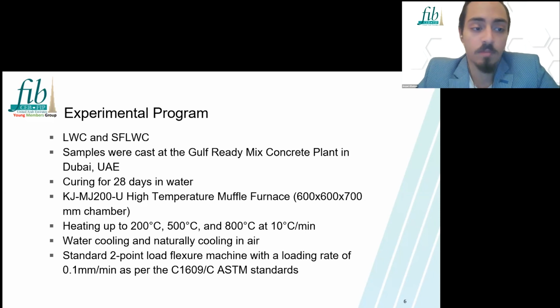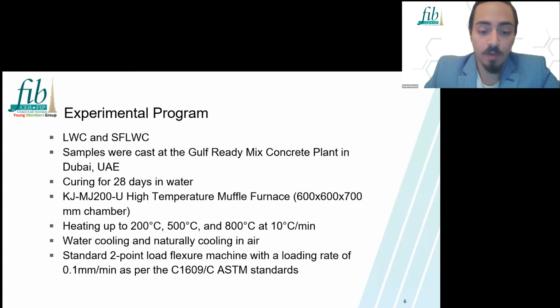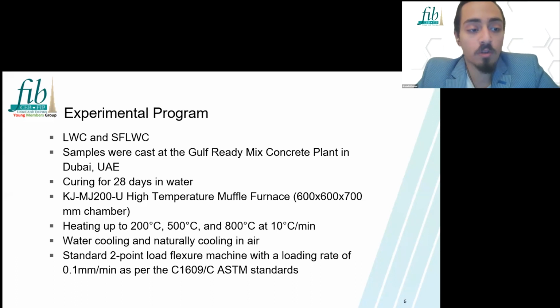This rate was also chosen because of how common it is in the literature. We had 8 samples for every temperature, 4 for lightweight and 4 for steel fiber lightweight concrete. Now, after heating, we took the samples out of the furnace and subjected them to either water cooling, which is just dipping them in water, as I will show you later on, or we left them to cool naturally in air. For testing the prisms, we placed each prism in a standard 2-point load flexural machine with a loading rate of, as you can see, 0.1 mm per minute as per the ASTM standard.